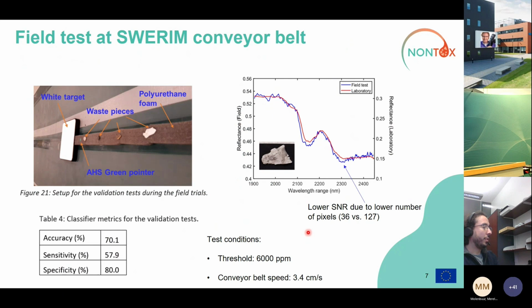And this is a summary of results of the field test, because this sensor was also implemented in an actual pilot test bed at Swerim in Sweden. And one of the tests that we did here was this validation of the lab results, which I'm showing in this picture. So this is just a reflectance target for the sensor. This is a green pointer to show where the beam is. And we have a sequence of plastic waste pieces here. These were the pieces that we analyzed in the lab, and they were also analyzed on the conveyor belt.